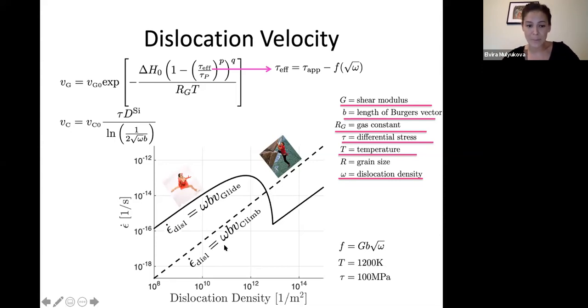So here I'm just showing you an example where I'm plotting the strain rates as dictated by Orowan's equation. So these velocities times some dislocation density. So the typical strain rate for varying dislocation density. And glide here is shown as a solid line. So at low dislocation densities, or relatively low dislocation densities, glide is efficient compared to the climb velocity. So the strain rate will predominantly be accommodated by that. However, once you reach a high enough dislocation density, glide becomes difficult due to the interactions between different dislocations. And so climb may eventually take over.